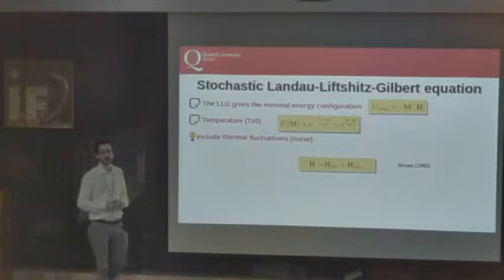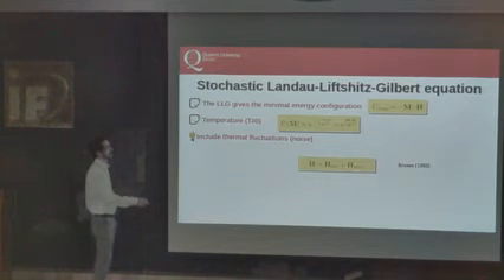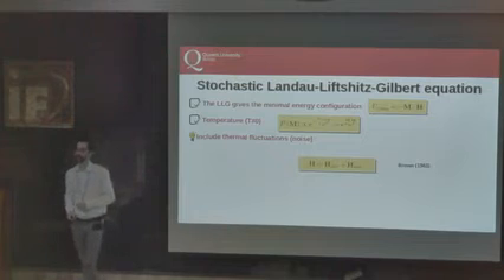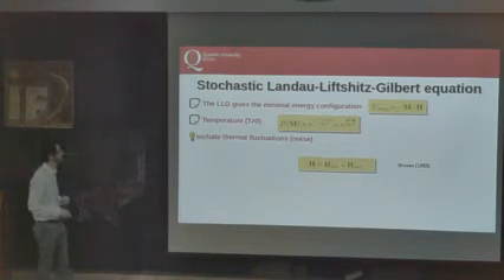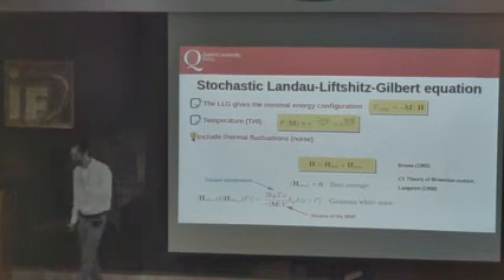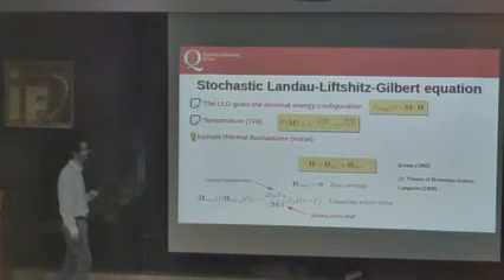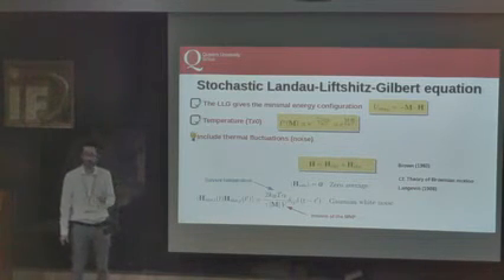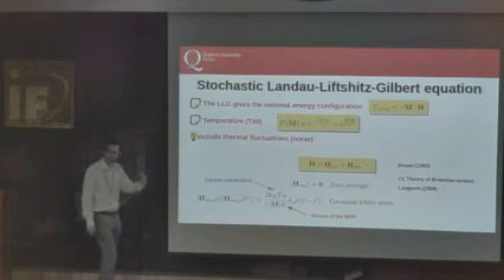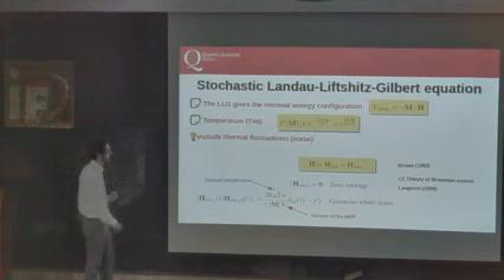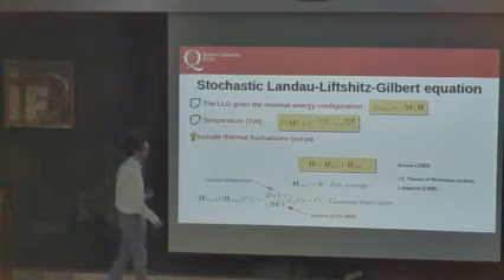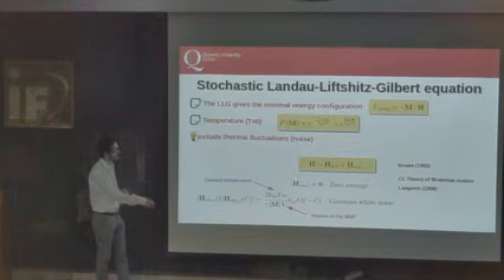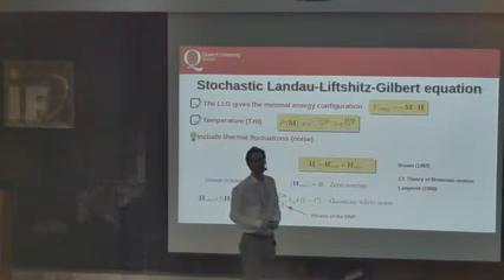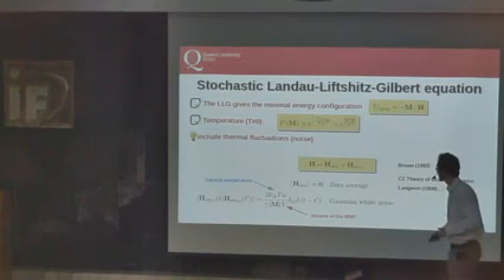In order to introduce thermal effects, we have to introduce thermal fluctuation in the same fashion as for the Langevin equations. And so there will be a stochastic term, already mentioned, added to the deterministic term. And that has been pioneered by Brown, not the Brown of Brownian motion, of course, some century after. So again, more explicitly, how are the correlations and the averages for this stochastic process, which gives the fluctuating thermal magnetic field? It has zero average. There is no net effect. And then the fluctuations are still white noise, delta correlated, and they depend again, through alpha, through the viscosity, the temperature, and then also the volume of a nanoparticle. If you have a large nanoparticle, you can imagine you won't see these fluctuations. And this is why we have the volume there.